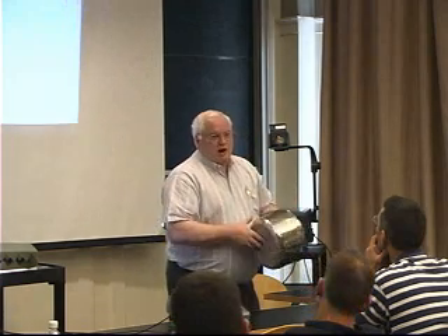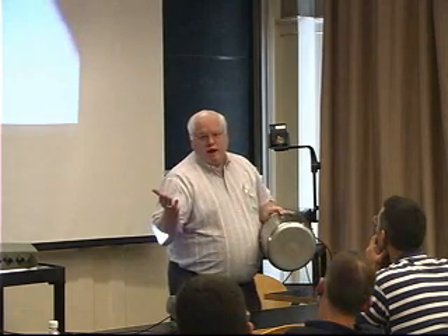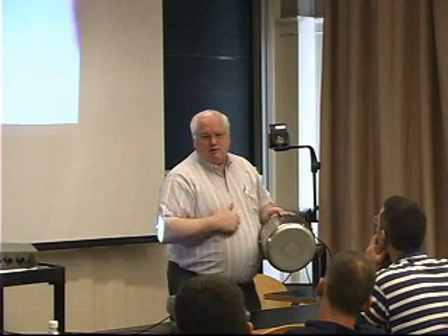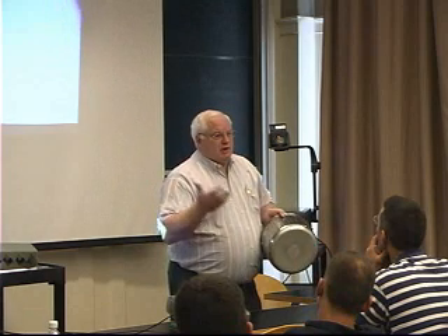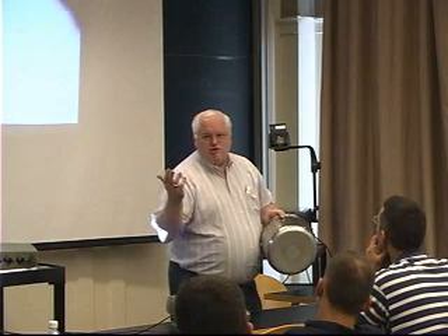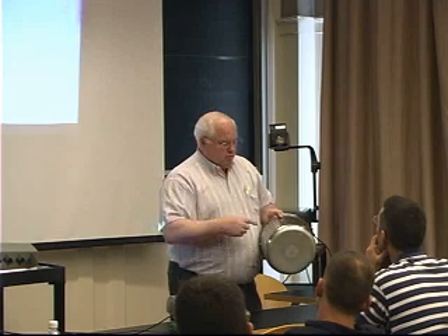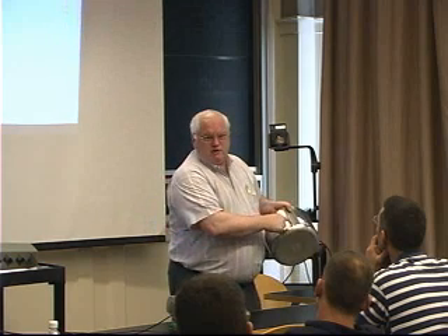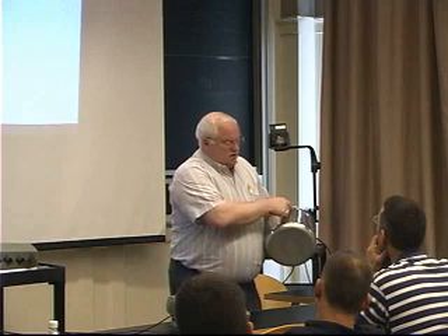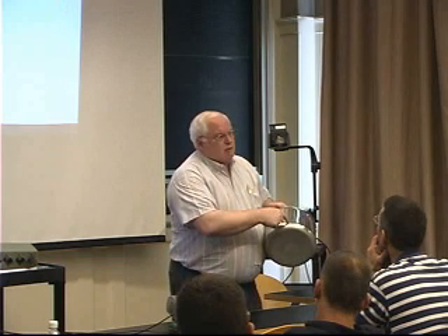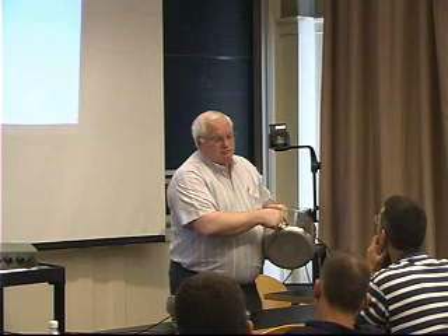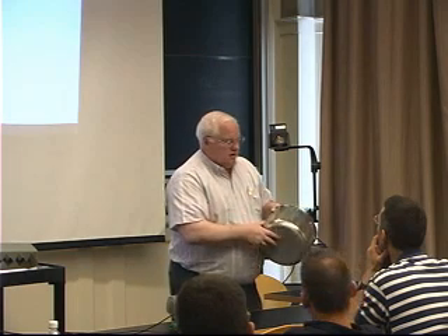Why are we getting these cracks? Well, first of all, they told me they're delayed cracks. They didn't show up until they got to Japan. Well, what does that tell me? Delayed cracking, to me as a metallurgist, means hydrogen embrittlement. Hydrogen embrittlement doesn't occur in 304 face-centered cubic stainless steel. It does in body-centered cubic. These cracks were all starting up here and running down here and stopping because they ran out of body-centered cubic iron. Okay? So it all fit together.